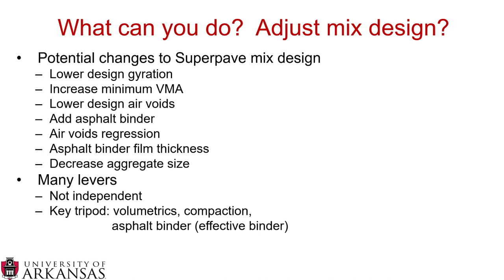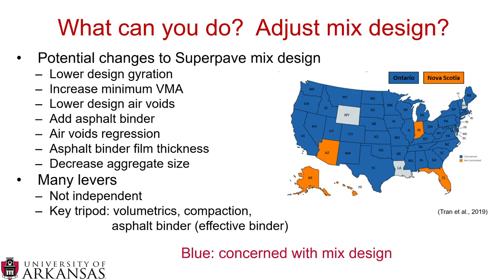And I've had a lot of conversations about this with various people, and I really think that there's a key tripod here. You have to think about your volumetrics, which includes VMA, air voids, VFA. You need to think about your compactive effort, which is your number of gyrations. And then you need to think about your asphalt binder content, or specifically your effective asphalt binder content. So what's coating your aggregates? If you change one of these and you don't change the other two, there could be issues with the other two, and it doesn't matter which one you look at. You can't just change one at a time, because then you're just changing the length of one tripod leg, which makes you unsteady regardless of how you hack away at the other leg. So you need to think of all three of these in concert.